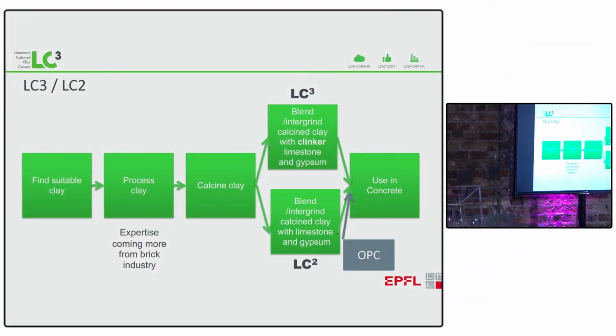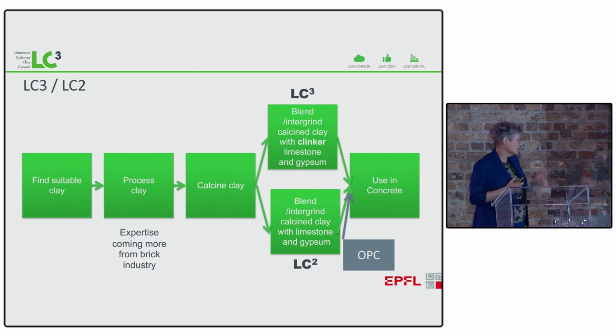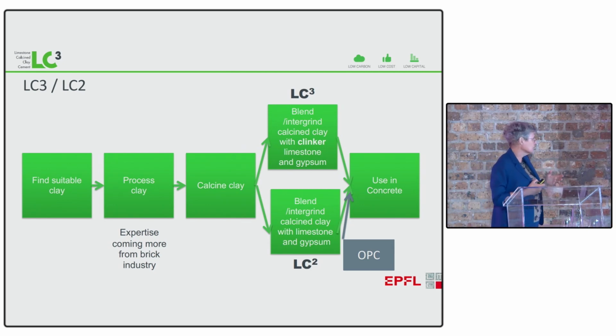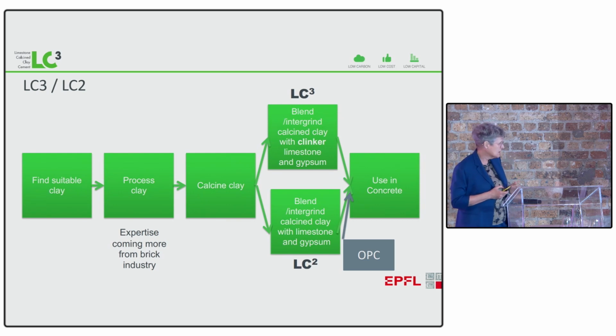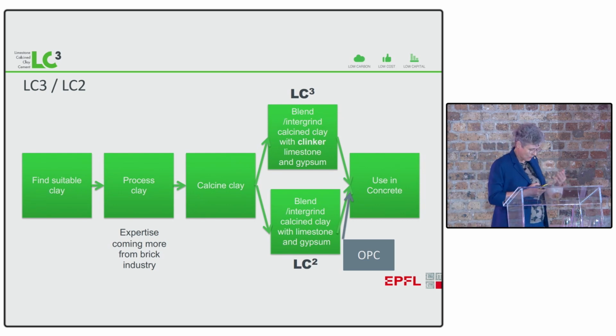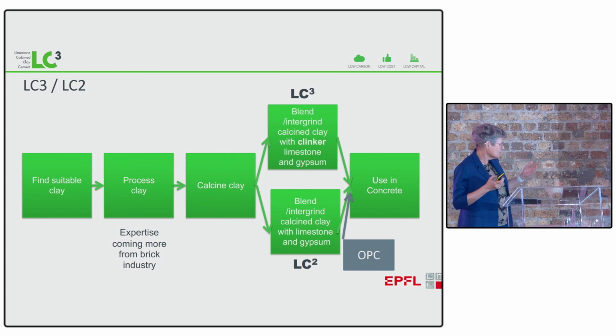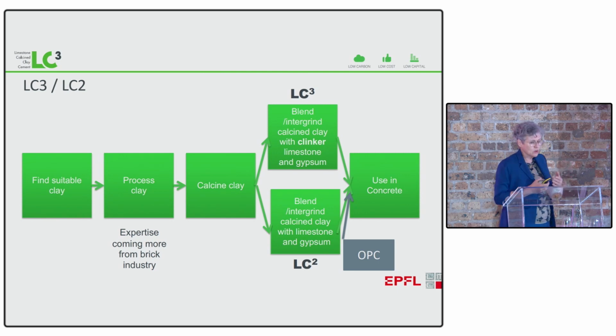Now, here I'm coming back to LC2 because, so far I've been talking about LC3, and LC3 is what happens when you mix all these ingredients together at the cement plant and you just use that as the binder to make concrete. Now, in several parts of the world, North America, UK, South Africa are the notable ones, the practice has been not to have blended cements where everything's blended together at the cement plant, but to add the additions like slag or fly ash at the concrete level. And you can do that. It's really exactly the same because at the end of the day, you end up with the same mixture in the concrete. And that's what we call LC2.